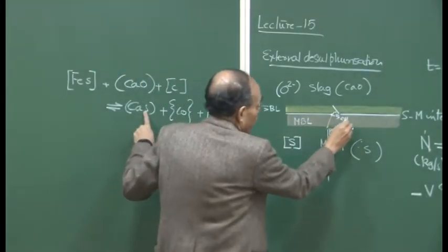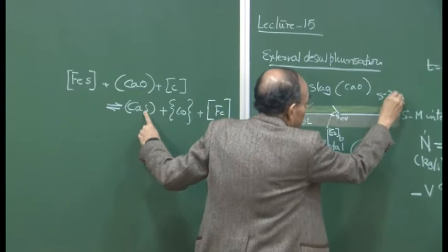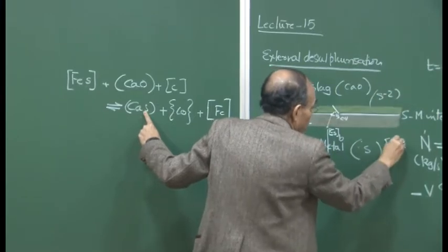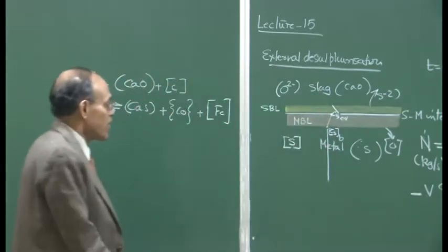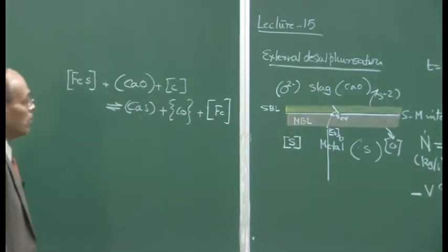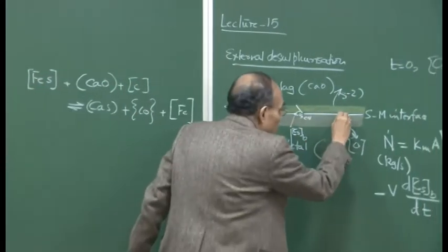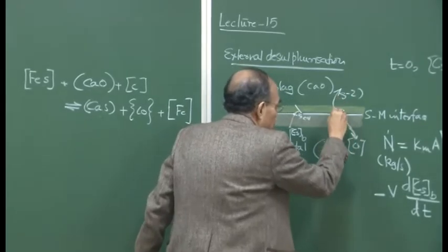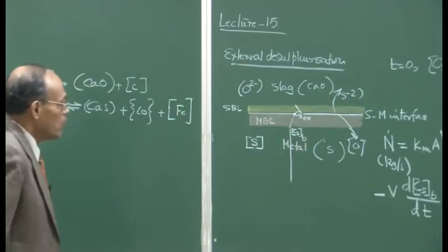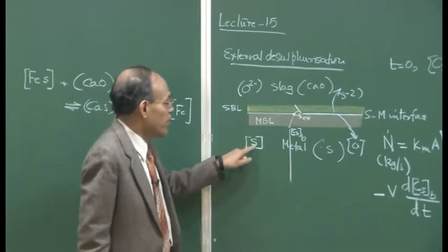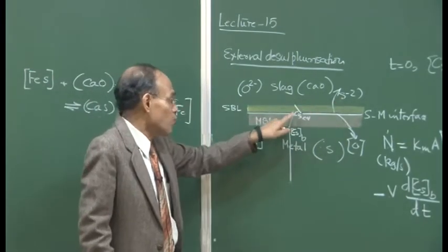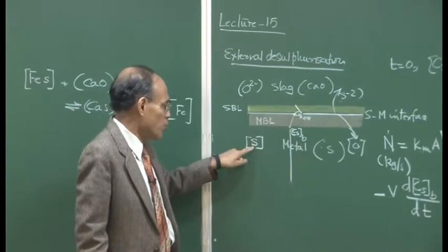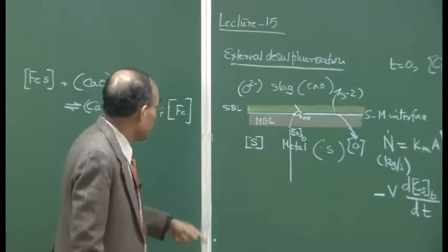Then the sulfur from here will go to the S2, and then oxygen is going to come here. So, that is the way the products are going to move from the interface. So, virtually whatever sulfur reaches here, immediately that sulfur is going to be converted to sulfide ion. So, we will come out to be a very small concentration of sulfur right at the interface itself.